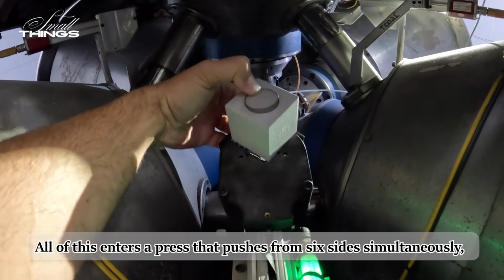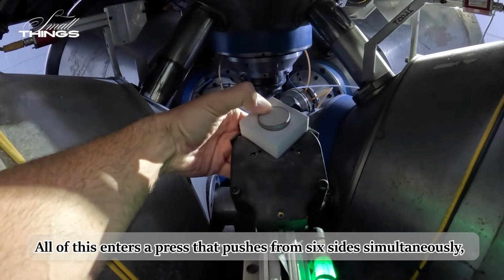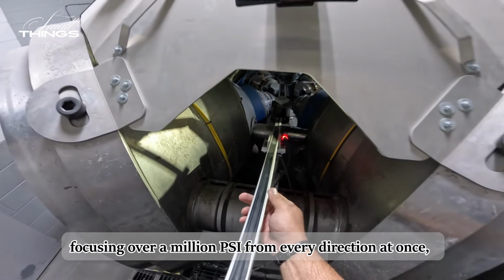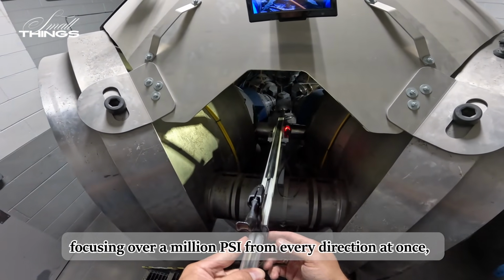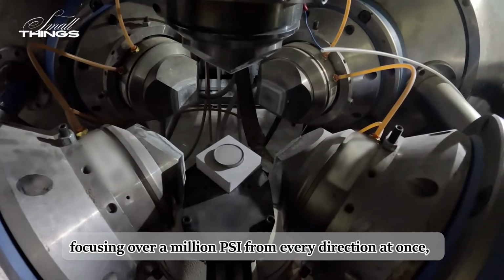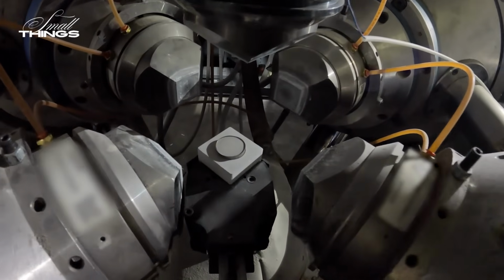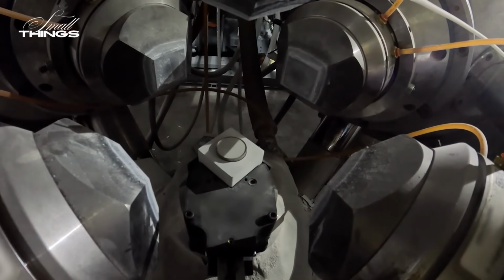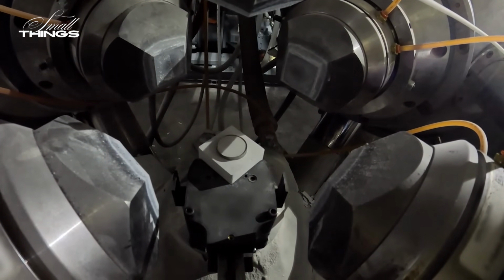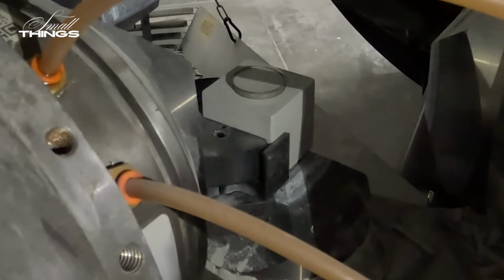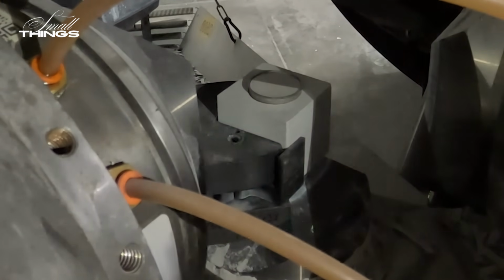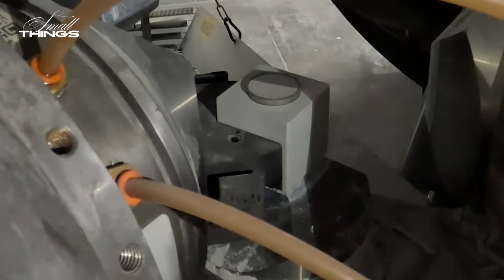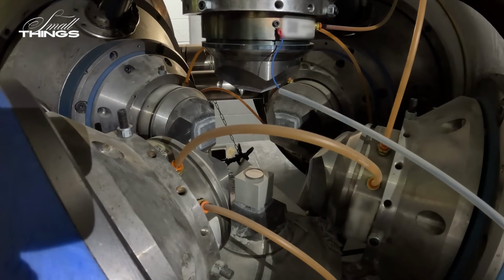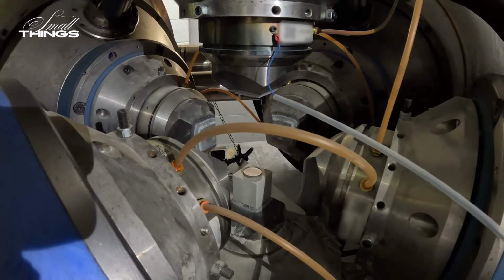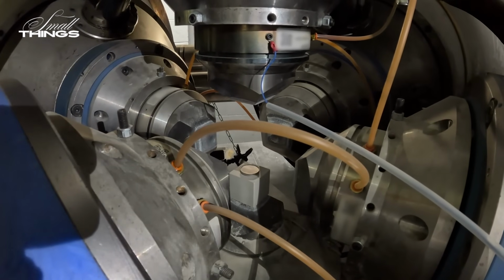All of this enters a press that pushes from 6 sides simultaneously, focusing over 1,000,000 psi from every direction at once, while electricity heats the interior to around 2,500 degrees Fahrenheit. At that temperature and pressure, the bonding process runs its course, and in roughly 10 minutes, what was loose powder has become one solid piece of material.